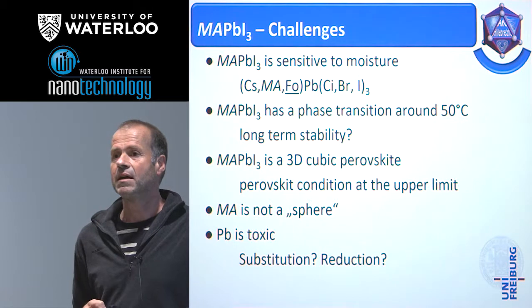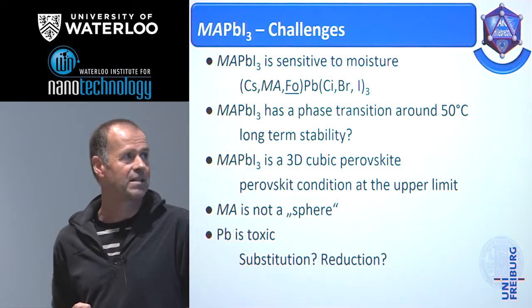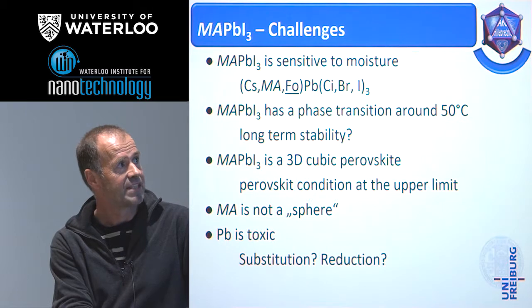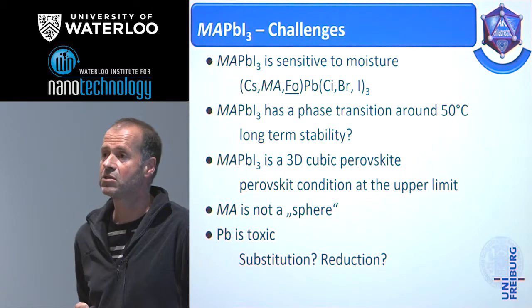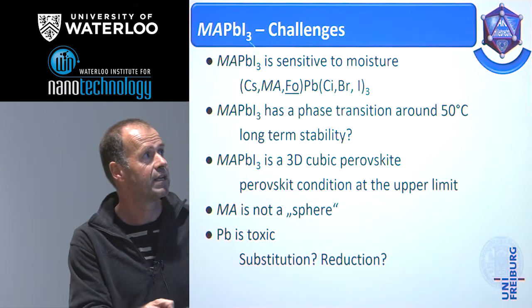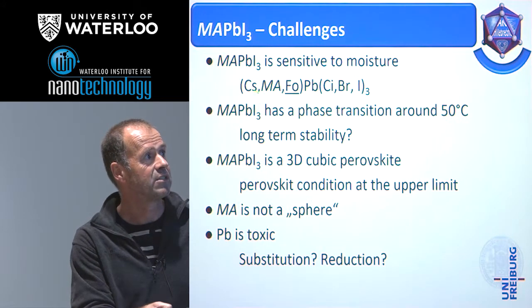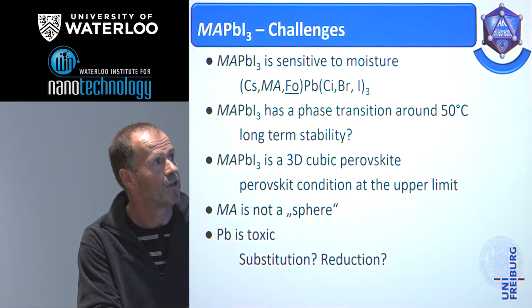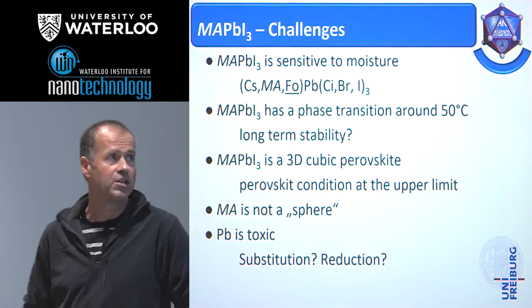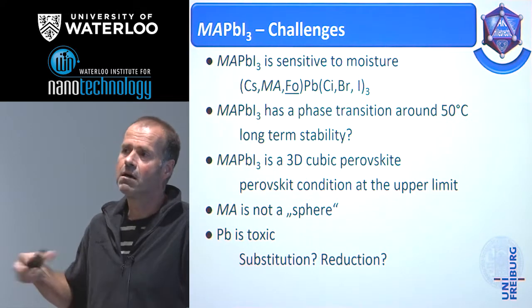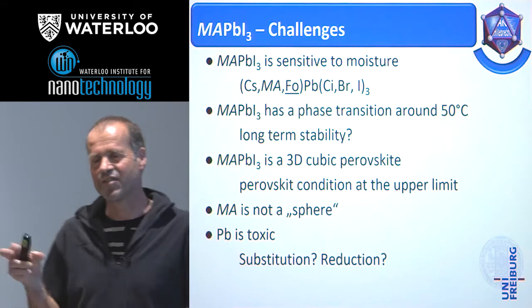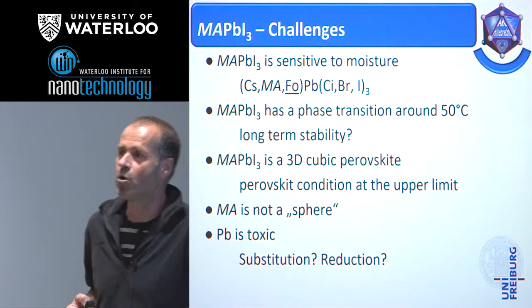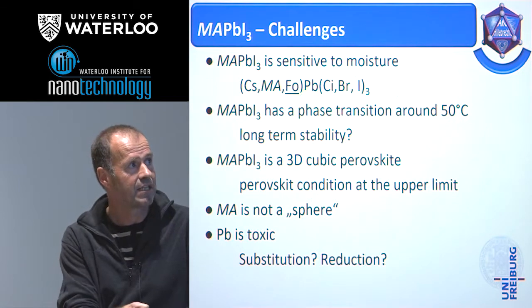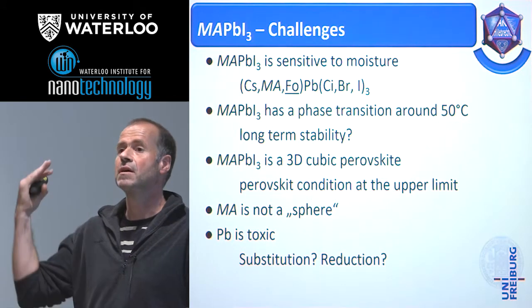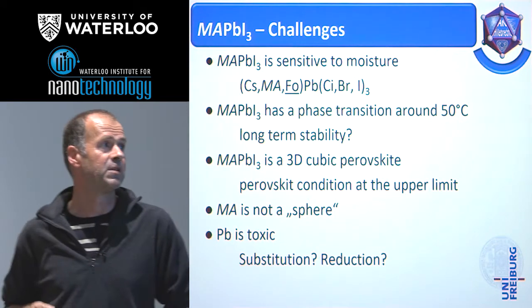Methyl ammonium lead iodide is great, but there are some disadvantages. One is the sensitivity to moisture. One idea to solve this problem was the substitution of the organic cation by cesium or formamidinium, or to change the halide. It was shown that the addition of chlorine makes the sensitivity a little bit lower, but it is not the uptake of chlorine; it changed the process of the deposition of the material.